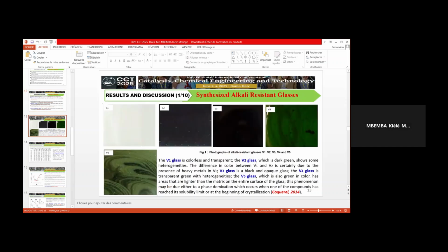Concerning results and discussion, for the synthesized alkali-resistant glasses, in figure 1 we can see photographs of alkali-resistant glasses V1, V2, V3, V4, and V5. You can see that the V1 glass is colorless and transparent. V2 glass, which is dark green, shows some heterogeneities. The difference between the two glasses, V1 and V2, is certainly due to the presence of heavy metals in V2.